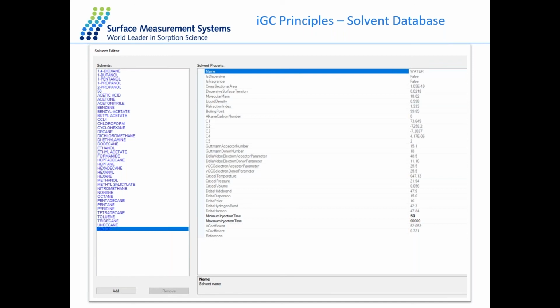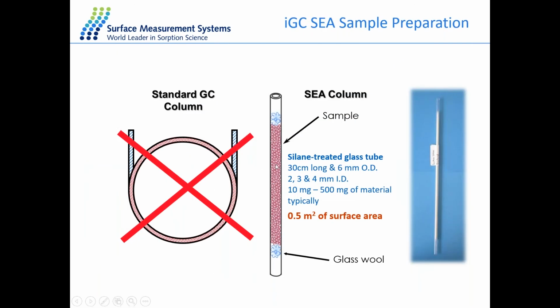And if you do choose to separate out the sample, we have done some column-to-column reproducibility studies, and it doesn't affect the results if you do use maybe some silanized glass wool in between to adjust the pressure. So we have done some column-to-column studies, and this doesn't affect the results.